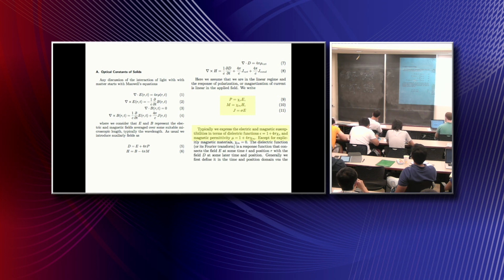But we come to the same point. Ultimately, if we had some experiment where we could measure the dissipative part of the response, the real part of the conductivity, this tells us how much energy is actually used when we're putting a finite frequency electromagnetic field in the system, then I can find the other part of the conductivity, and vice versa. Very frequently, we'll have some response of the system which has the real and the imaginary parts in it in some other, more complicated way. So we can use the real and imaginary conductivity together, import them into the Fresnel equations to figure out the reflection coefficient of some material.